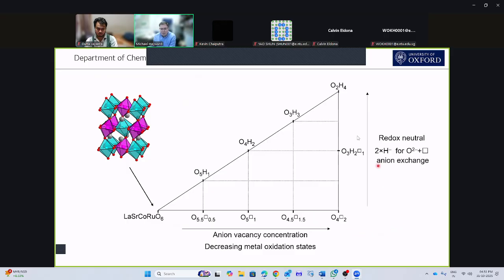And then moving up the phase diagram, what I'm doing is a redox neutral exchange of an oxide ion and a vacancy for two hydride ions. So I turn O4 with two vacancies ultimately into O2H4. And what we can do is put our phases that we've made on the diagram. So here's the phase from the calcium reaction, and here are the two phases from the lithium reaction. We can see these two are quite similar.